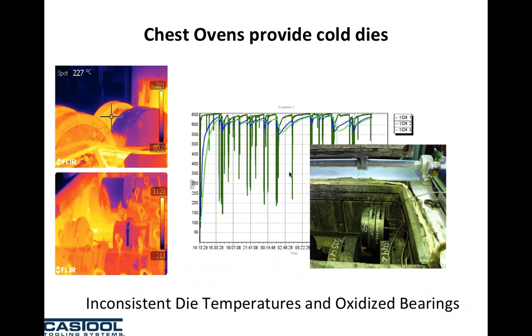I said it a number of times last week, and I guess a lot of people got upset with me: chest ovens don't work. If the goal is to have a die that's plus or minus 10 degrees Fahrenheit uniformly from billet temperature, and you're heating dies with chest ovens, it's impossible to do that. Chest ovens produce cold dies, inconsistent dies, and typically dies are in them for too long and have oxidized bearings.